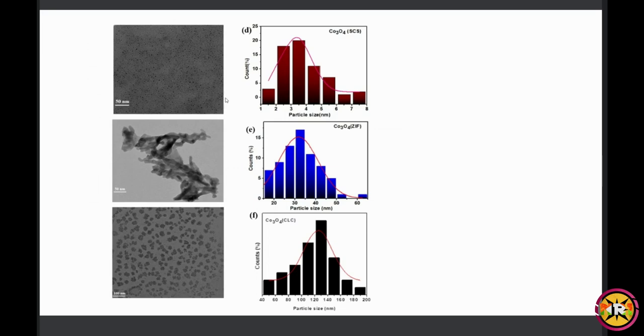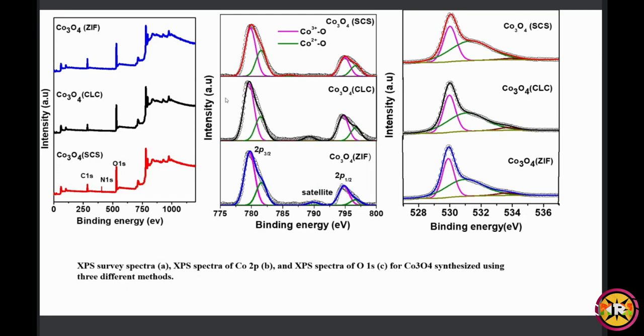So now coming to the TEM analysis. From TEM, I have calculated the average particle size of the three synthesized Co3O4, and here also I have observed the particle size of Co3O4 SCS is less than the other two. So from XRD, TEM and SEM, I can conclude that Co3O4 SCS is not purely crystalline. It's a nanostructure, and it has the higher surface area, pore size, and also less crystallite size. And even the oxygen occupancy is less than the other two.